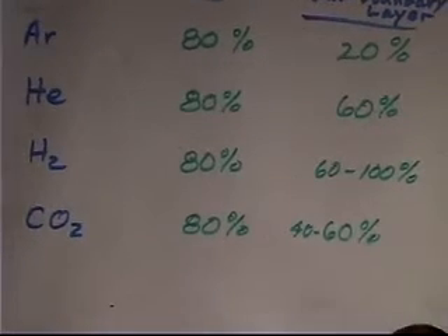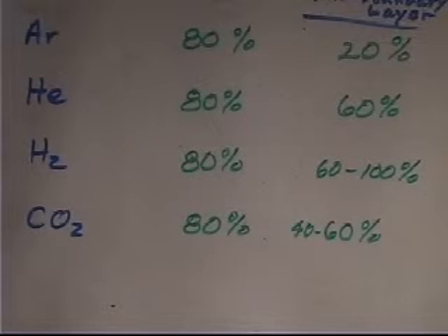Well, you can say who wants to weld steel in a 100% hydrogen atmosphere, but those cellulosic stick electrodes I talked about, I passed them around. The cellulosic electrodes, what's cellulose? It's a hydrocarbon, right? Turns out that atmosphere you generate by burning up the paper around that steel rod is about 60% hydrogen. So cellulosic electrodes are called high hydrogen electrodes. The 7018 electrode, which has the mineral coating, is called a low hydrogen electrode, or commonly called low-high out there in the industry.